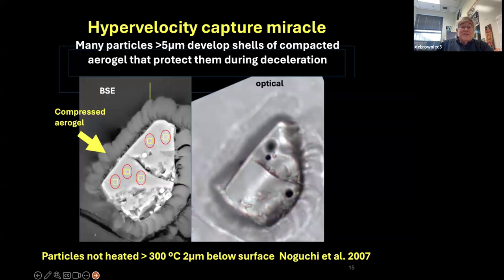Here's a particle. The circles and squares are areas triggered for analysis, for isotope analysis at Wisconsin. But you can see this cocoon around the particle. That's solid compressed aerogel, which is clearly protecting the material.